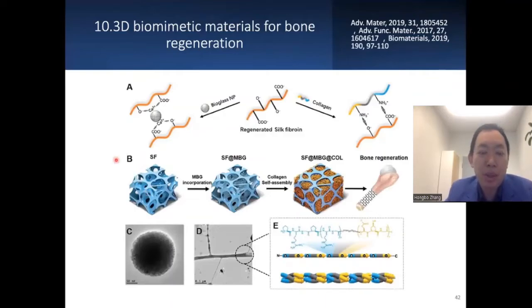And we also do some tissue engineering-based projects. For example, here we use 3D biomimetic material for bone regeneration. So the natural bone has a unique structure. And we are thinking, if we can highly mimic this structure, can we promote bone regeneration without using any drug? So here we first make this fiber as a scaffold, and this scaffold is mimicking the hard part of the bone. And then we seeded this bioglass into the structure, and they are mimicking the nanoparticles in the bone. And then we put this collagen to fill this structure, and collagen is mimicking a bit softer part of the bone.